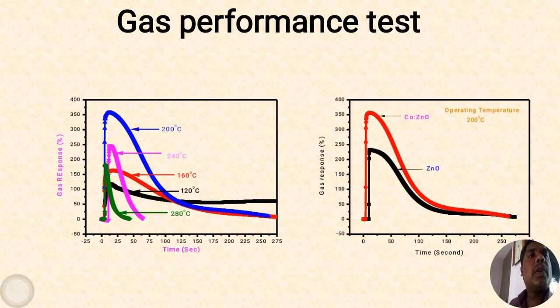Now, the next task is the gas performance test. Firstly, we checked the temperature effect on our nanostructure, and for that purpose, we took the temperature in the range 120 degrees Celsius to 280 degrees Celsius, and we got the maximum gas response at 200 degrees Celsius. That is an amazing result at 200 degrees Celsius and 100 ppm NO2 gas concentration, therefore that is the optimum temperature as well as optimum concentration for further analysis.